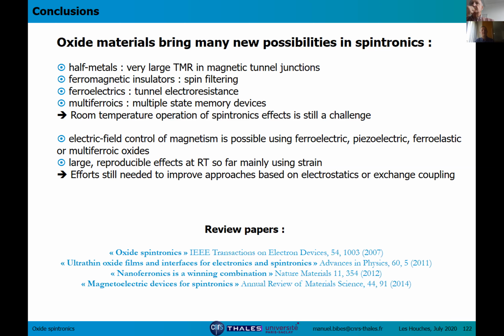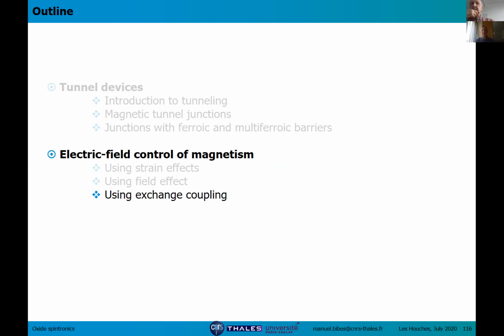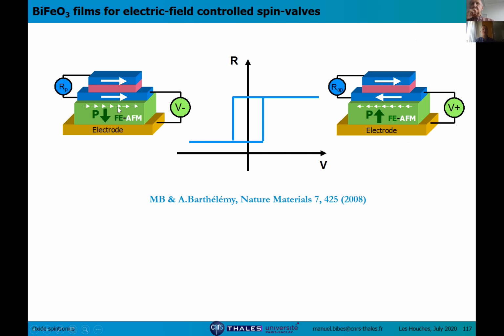It's a lot of trouble because if they were ferromagnetic, the coupling with, I mean, in the device I was showing, yeah, this device, if the ferroelectric was also ferromagnetic, then the coupling with the bottom layer here would be much stronger. Here the coupling is quite weak because it's related to the weak moment of BFO. So BFO is not exactly a pure antiferromagnet. It has also a weak canted moment. And as I understand it from the results of Ramesh, the coupling is between the magnetization of this bottom blue layer and the weak moment of the bismuth ferrite. So the larger that moment, the stronger the coupling. So if it was a proper ferromagnet, it would be much easier.